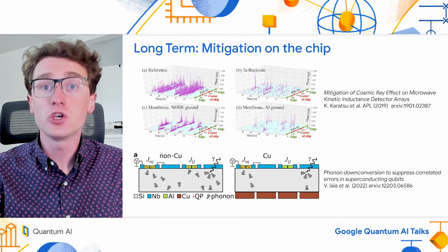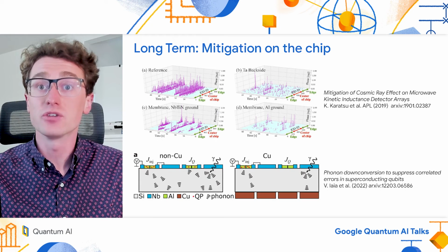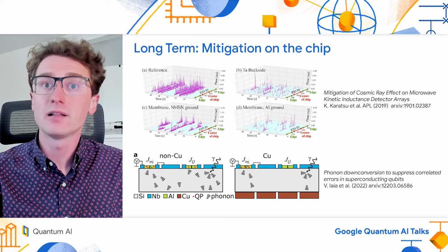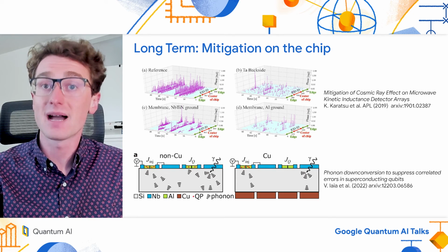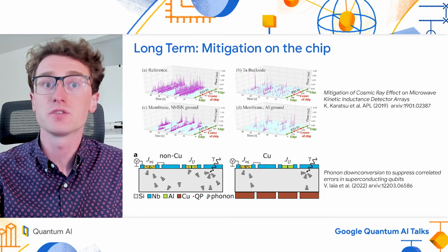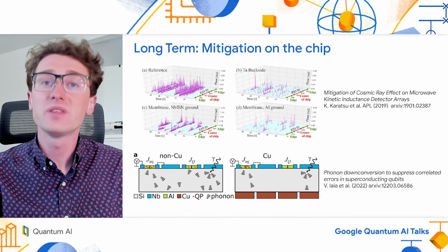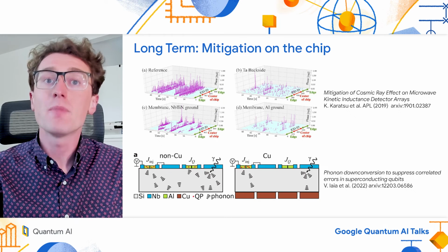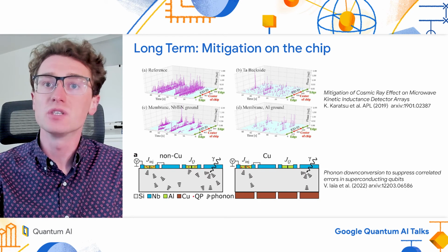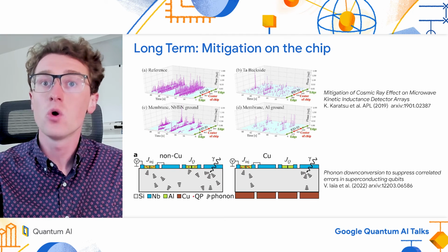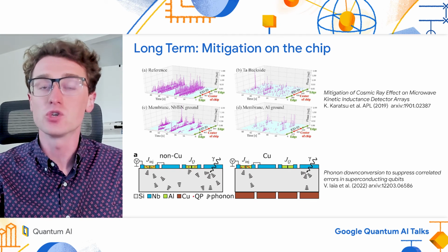More recent work on qubit devices has shown similar mitigation is really promising, such as a recent experiment shown here, where a normal metal phonon down converter was added to the backside of the chip to absorb hot phonons propagating in the device. With these strategies well within our ability to fabricate, the remaining challenge is really integrating these solutions into the large, complex quantum processors without decreasing coherence or gate performance. And that's a demanding future task for us.